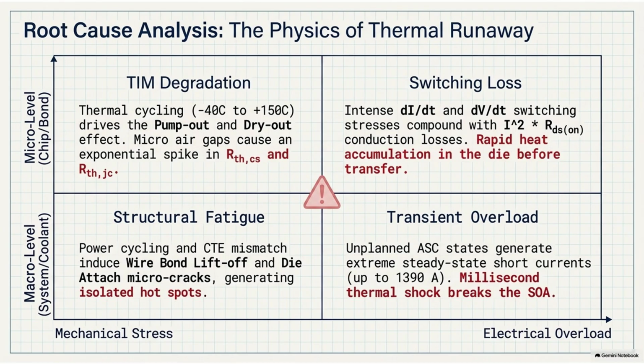This is a phenomenon known as wire bond liftoff. Alternatively, the solder material acting as the glue under the chip cracks, causing delamination. The consequences of that are terrifying because it's a nonlinear compounding failure. How so? Well, when those microscopic wires start snapping, you lose electrical pathways. That means the remaining intact wires suddenly have to carry more current, right? Their electrical resistance shoots up, which creates more heat. But simultaneously, because the bond is broken, you've lost thermal pathways, meaning less heat can escape. It is a textbook death spiral.